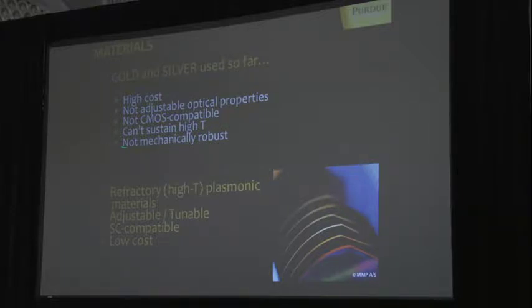This is what people don't discuss much, but I think it's a very essential problem. The whole idea of plasmonics is to focus light down to the nanoscale. But when you do that, you have elevated, really high energy density, and it's unavoidable that the temperature rises. It increases typically by at least, let's say, 400 Celsius. And if you're dealing with nanostructures, the truth is it's enough to destroy your structure.